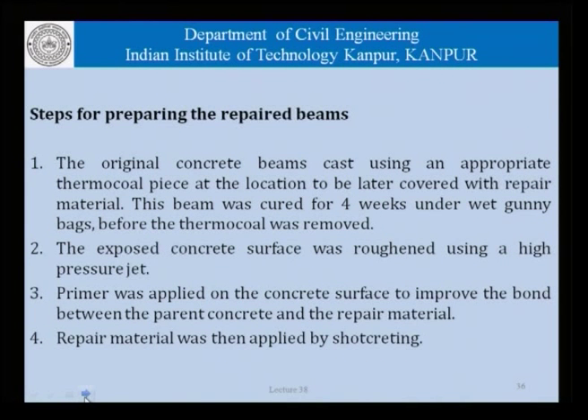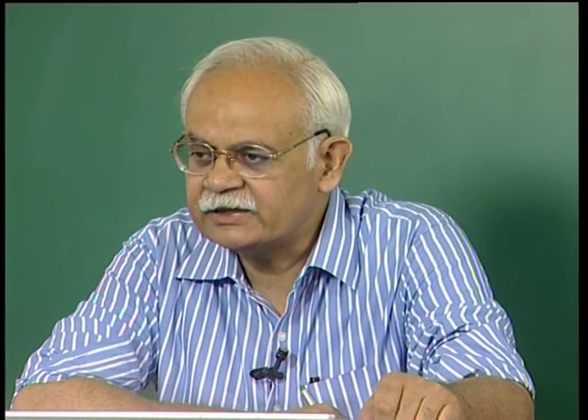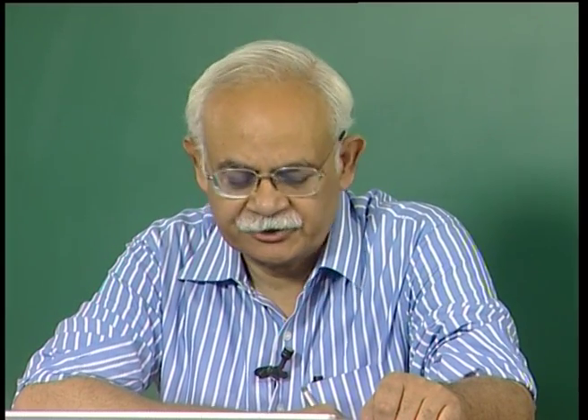The original concrete beams were cast using an appropriate thermocol piece at the location to be later covered with repair material. This thermocol piece was obviously removed at the time of placing the repair material. The beams were cured for 4 weeks. The exposed concrete surface was roughened using a high pressure water jet, and primer was applied at the concrete surface to improve the bond between the parent concrete and the repair material, and that is typically done even when we are carrying out the repair and reinforcement work in a site. And the repair material was applied using shotcreting, whether it was cement based or it was polymer based. In this case, the repair was done using shotcrete.